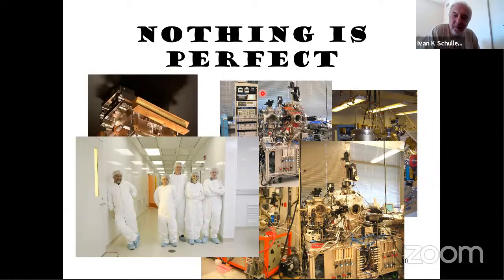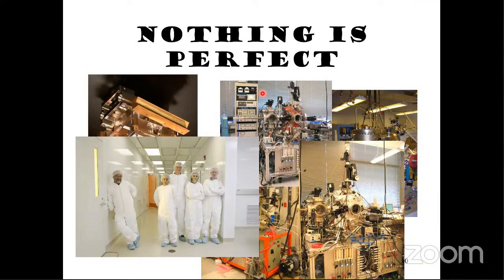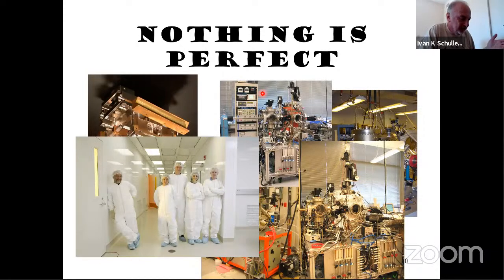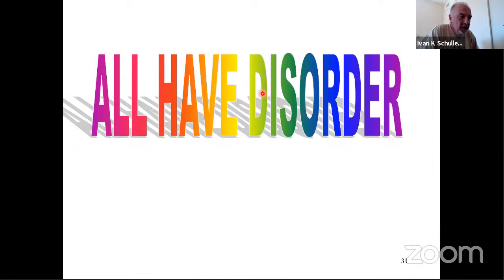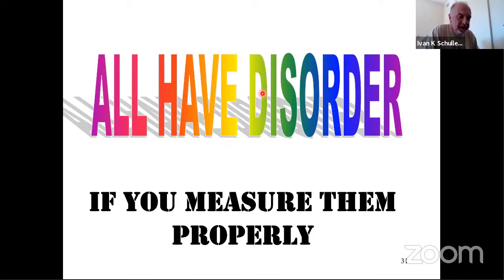The reason it's going up is because it forms this iron oxide layer, which is a ferromagnet. As you're cooling it down, the iron oxide magnetic layer starts taking on the signal. So there is a magnetic oxide layer, which has a transition temperature around the very same transition temperature of the vanadium oxide. And therefore, there is a magnetic moment that goes up. Okay, and increases. Okay, thank you. That's all that you are seeing. So it's kind of an uninteresting thing, but it's masked by this complicated thing and all the structure. So you have to be careful. That's all I'm saying. Okay, so all materials have disorder if you measure them properly. That's what I want to argue here.